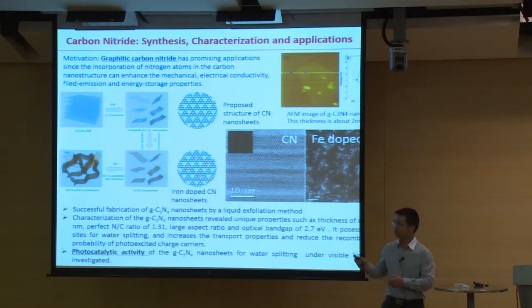Okay, here's the next part of the story, on boron nitride and carbon nitride. Carbon nitride is kind of strange because, unlike graphene and boron nitride, the atomic structure of carbon nitride is not that stable, or maybe not that fixed. So it's really hard to get a TEM image of what the carbon nitride looks like. Here we use commercial bulk carbon nitride and use the liquid exfoliation method. We can get some atomic layers of carbon nitride. And we can get some TEM images showing the atomic structures of the carbon nitride, and also showing the diffraction patterns here. And also we can dope iron into this lattice. This iron can be individual iron atoms or a cluster of a few iron atoms. And this material actually is a very good catalyst for water splitting, that is, hydrogen evolution.